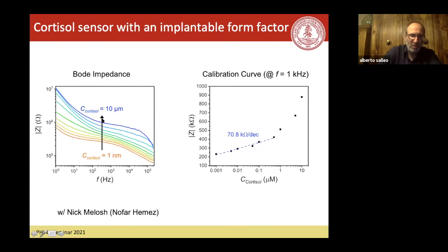Again, not super sensitive, but definitely measurable, and not super sensitive because Nofar didn't work super hard on making it very sensitive. In the end, what you want is sensitivity in a reduced range, because cortisol will not go. Sorry, this should be micromolar with a capital M, because cortisol will not go to very high concentration. So you want to tailor the device for the right concentration. We haven't really looked very much into that, but it's certainly feasible. Not super sensitive again, but it works.